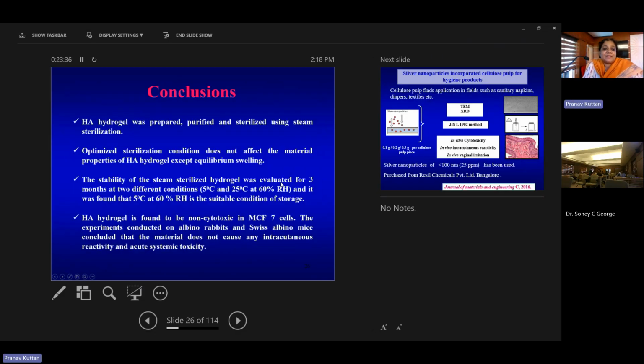So the conclusion for this work is that HA hydrogel was prepared, purified by dialysis, and sterilized. Again, I didn't mention that. Generally, medical devices are sterilized using gamma radiation. Most of the products we use are done by 25 kGy gamma radiation. That is a standard protocol. But these hydrogels are very soft material. If you do 25 kGy gamma radiation, it will all break. So we had to find some other method, and we optimized autoclaving, that is, steam sterilization. By trying different variations, we took the material and tested for sterility, and that is how we optimized the steam sterilization method.